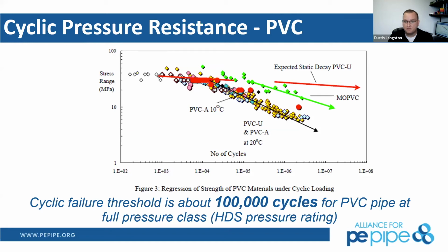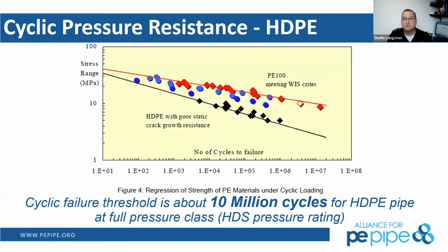So for PVC pipe, you can handle about 100,000 cycles. For HDPE pipe, we have testing now that shows we can have over 10 million cycles. Cyclic fatigue is not a design criteria for polyethylene pipe. It's just not a means of failure for us.